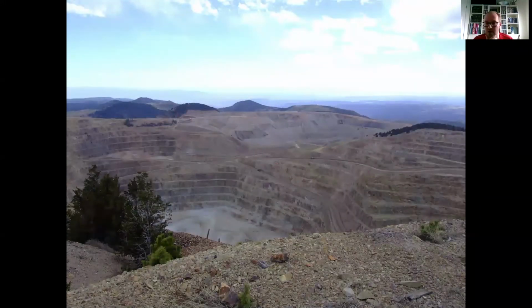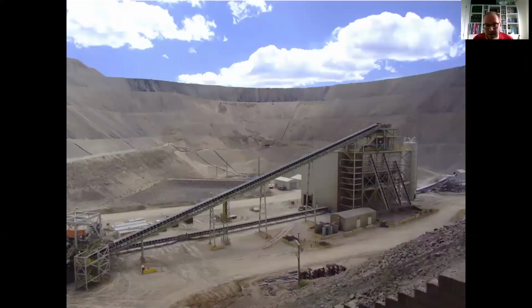So this is Cripple Creek. This is in Colorado. It's a phenomenal mine. It's a huge pit. Now extracting quite a lot of their gold by heap leach processing. So they're in some quite low grade portions of the deposit now, but it's been a producing world-class deposit for over 100 years. So here are the heap leach pads. In this case, they're using a dilute cyanide solution to extract the gold.